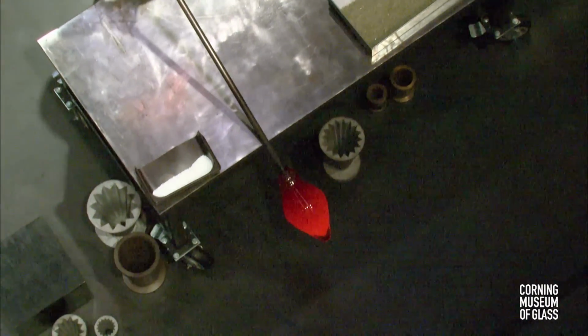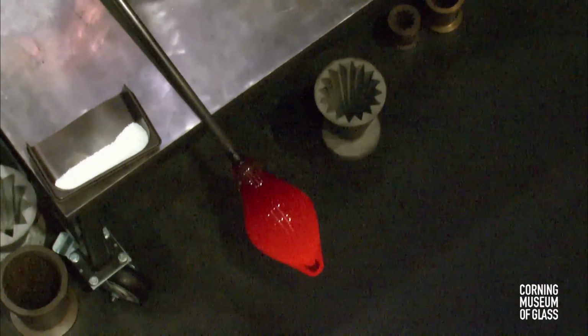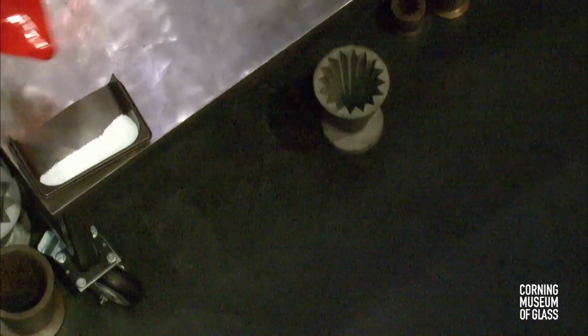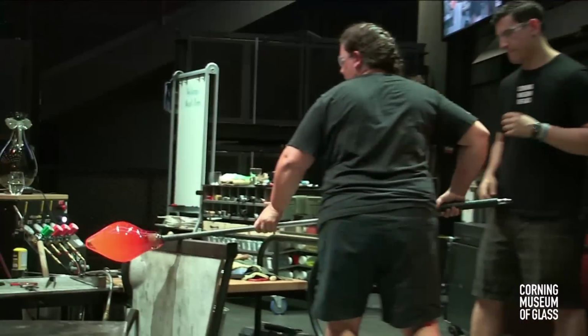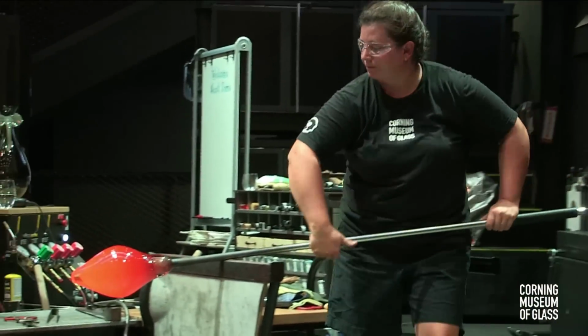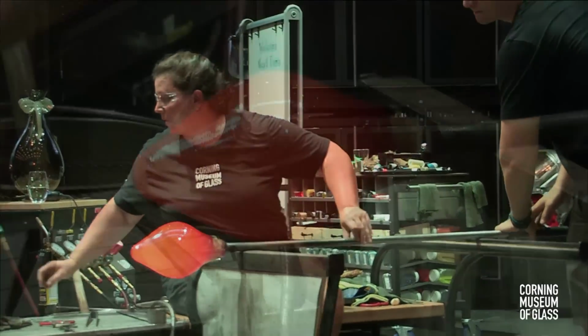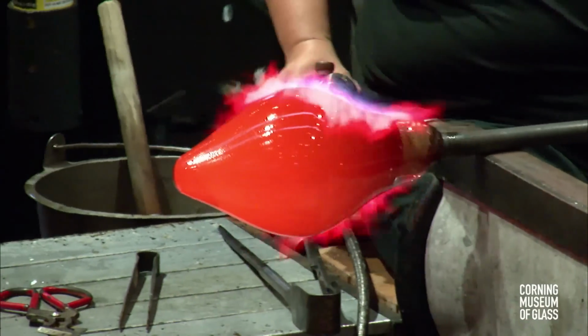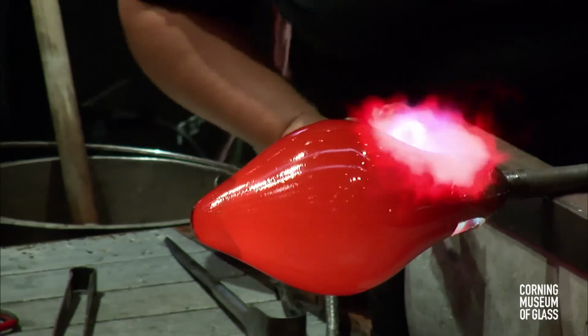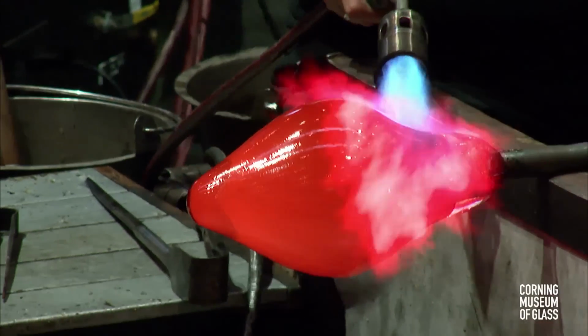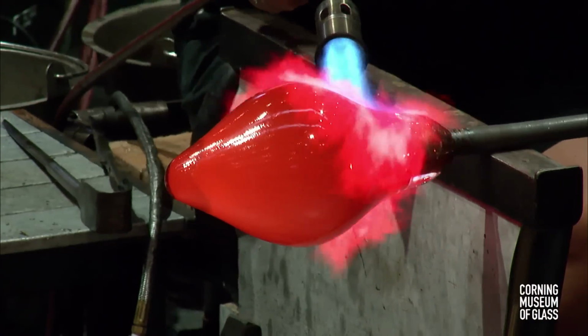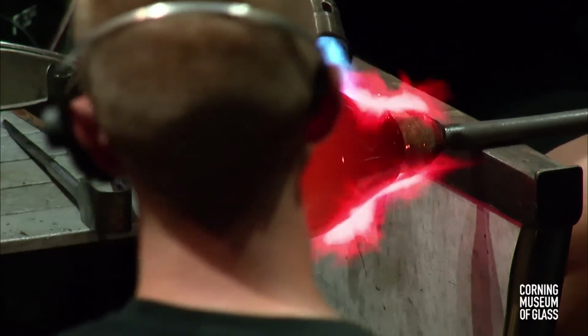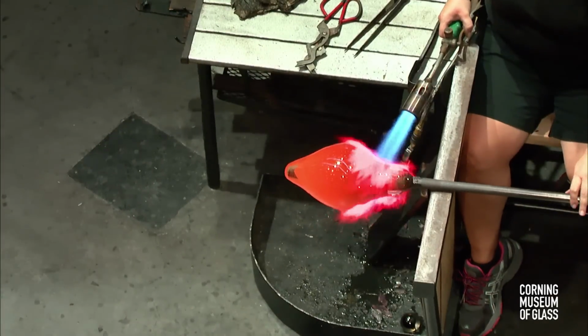If you stop to turn the other way, you've marvered or touched that glass twice with a cold metal table. You're going to take away the heat from a certain edge. You'll have an uneven heat around the entire bubble. If you go to blow that up, the air only goes the path of least resistance, so you're going to blow up the hot side. Meanwhile, the cold side you hit with the marver twice is going to stay rock solid.